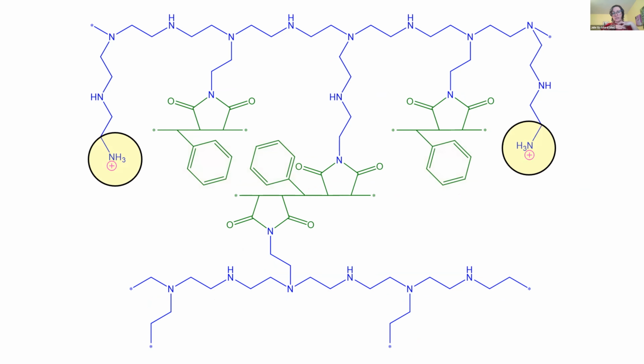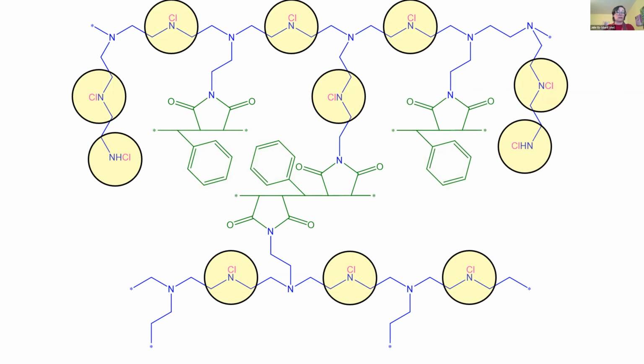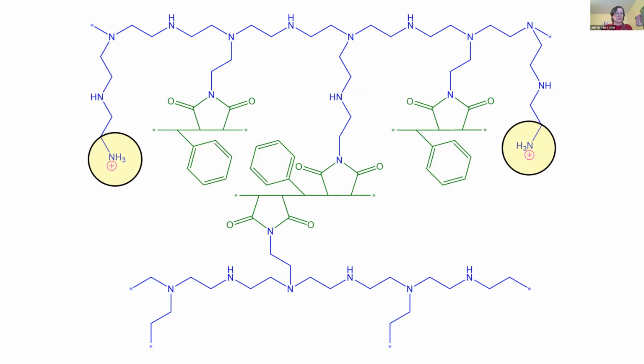We also, in doing so, made it so that there remained some cationic antimicrobials. So this is a little bit closer in performance and functionality to a quaternary ammonium compound. So this way we've got a dual mode antimicrobial character, so that even if the chlorinated halamines lose their chlorination, there remains some potential antimicrobial character through these cationic compounds.